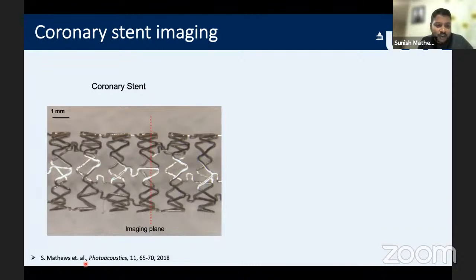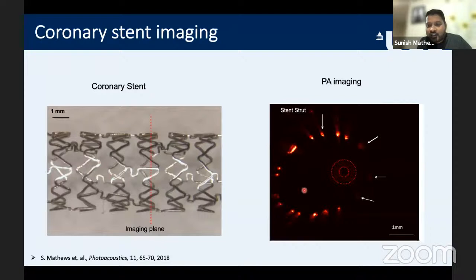And let me show you the image here. As you can see, that is the image that we are getting from this stent. The probe is somewhere here, and then the ultrasound sensor is on this side. So you get bright images from these parts of the stent, whereas you still get some region where the OCT probe is blocking the ultrasound sensor. So you get nearly 360-degree circumferential imaging with this system. This is just to test that our probe works and it can provide circumferential photoacoustic imaging. The light from the OCT probe falls on the strut, which generates a photoacoustic wave, and that is detected by our ultrasound sensor.